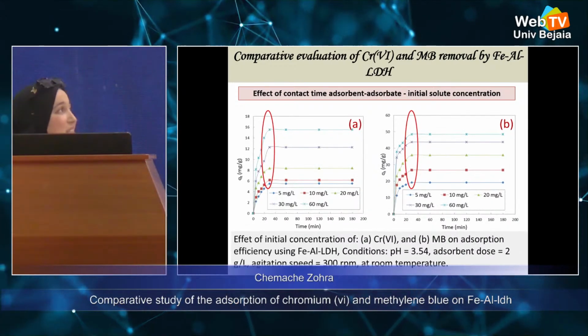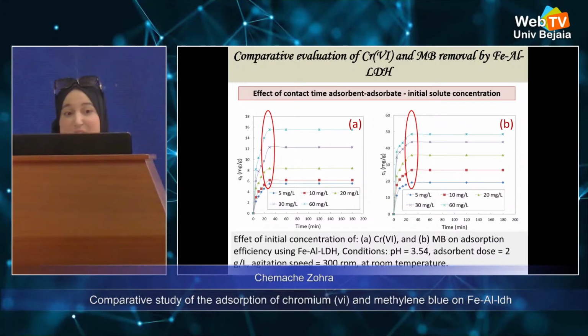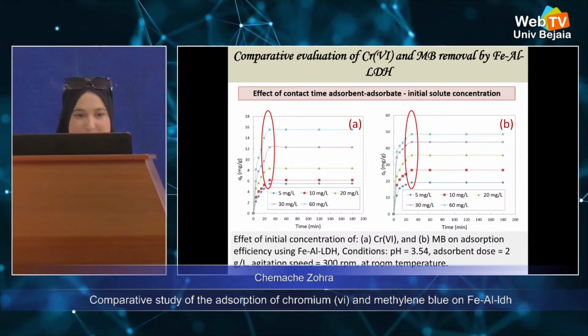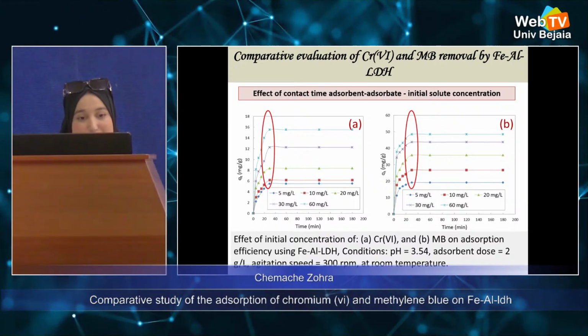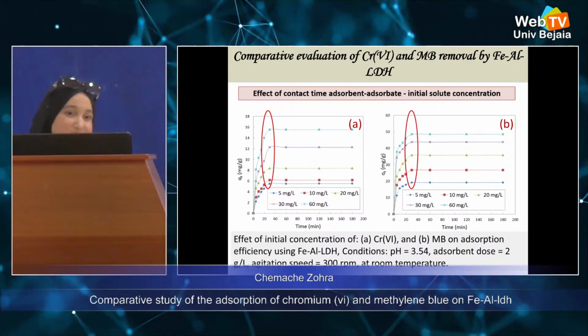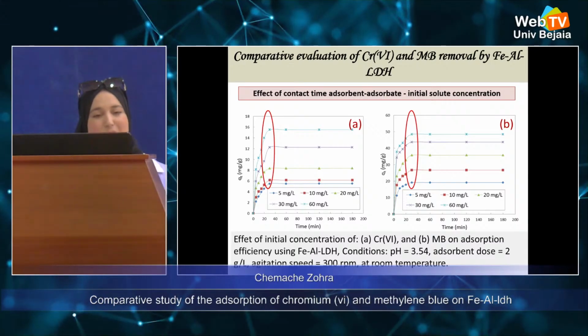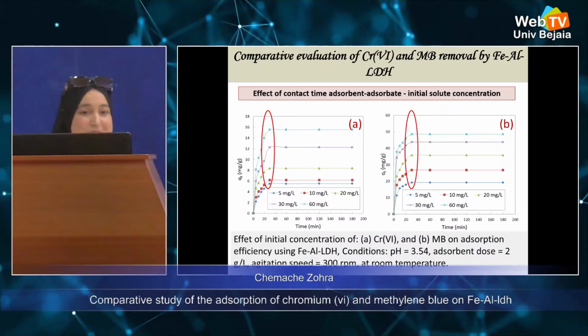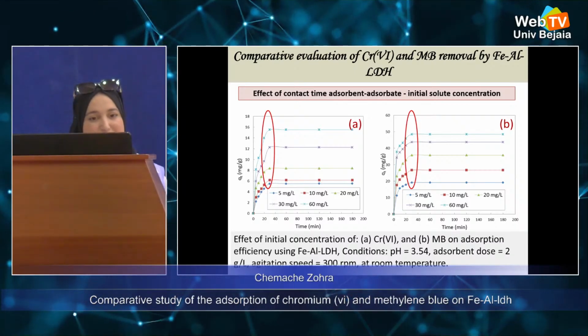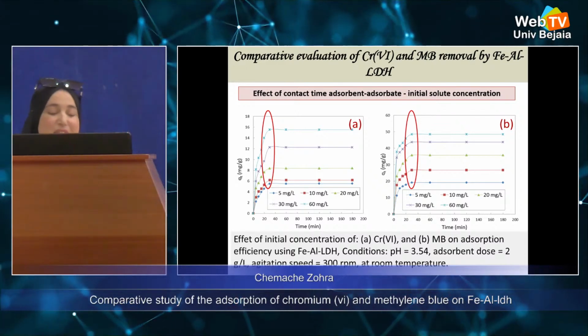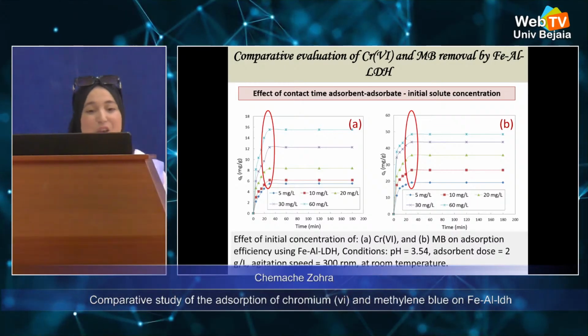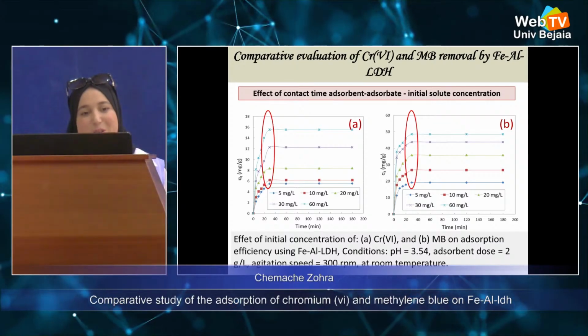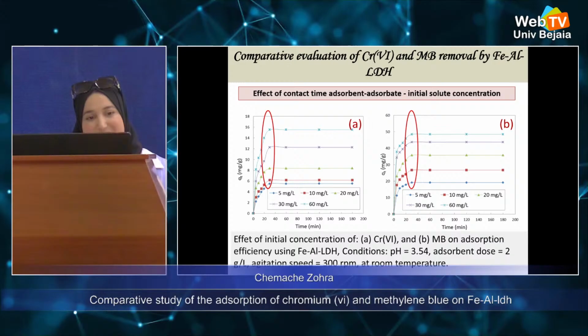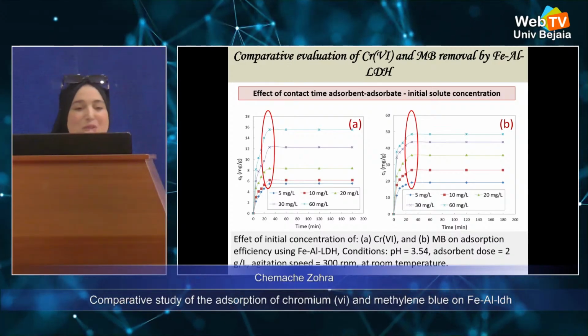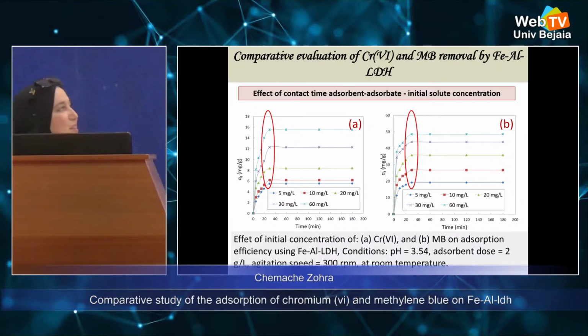The results shown in this figure reveal the same trend for both systems. Adsorption kinetics are rapid in the early stage and gradually slow, where the equilibrium is approached around 30 minutes. We also observed that adsorption efficiency increases with the increase of initial concentration, reflecting the stronger gradient of concentration between the solution and the adsorbent surface.